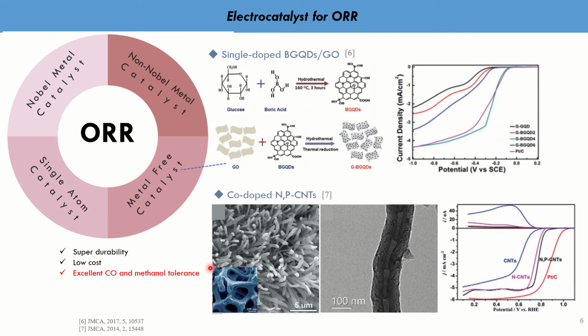Carbon materials including carbon nanotubes, graphene oxide, reduced graphene oxide, and graphene quantum dots have superior performance and electrocatalytic activity toward ORR. Graphene quantum dots can provide abundant active sites such as edges, functional groups, and doping heteroatoms such as nitrogen, sulfur, or boron, modifying their chemical and electrical characteristics by modulating the electronic structure of nanocarbon. The difference of electronegativity between boron and oxygen atoms allows easy adsorption of oxygen molecules on boron atoms, which leads to the subsequent oxygen reduction. Therefore, synthesized boron-doped nanocarbon might be a predominant strategy for metal-free carbon-based electrocatalysts toward ORR.